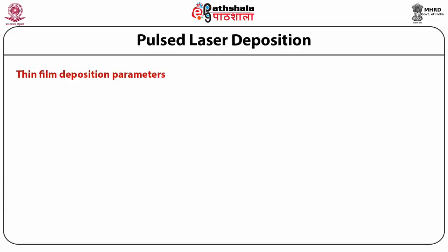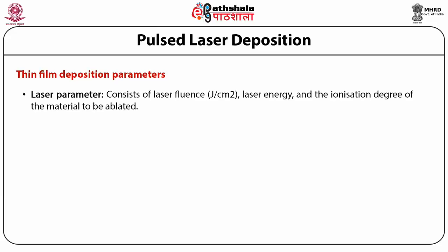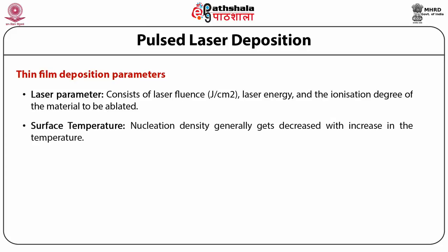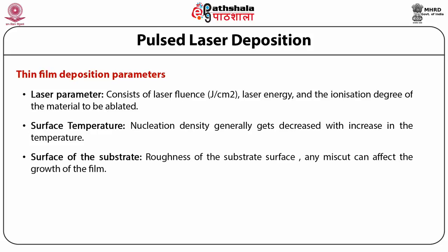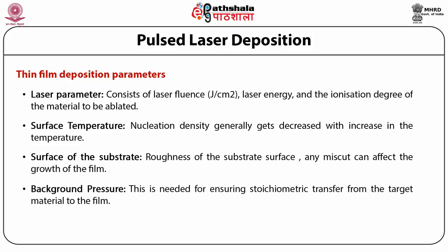Thin film deposition parameters in the case of PLD. First is the laser parameter. It consists of laser fluence in joules per centimeter square, laser energy, and the ionization degree of the material to be ablated. Second is the surface temperature. Nucleation density generally gets decreased with increase in the temperature. Third, surface of the substrate. Roughness of the substrate surface. Any miscut can affect the growth of the film. Lastly, the background pressure. This is needed for ensuring stoichiometric transfer from the target material to the film.